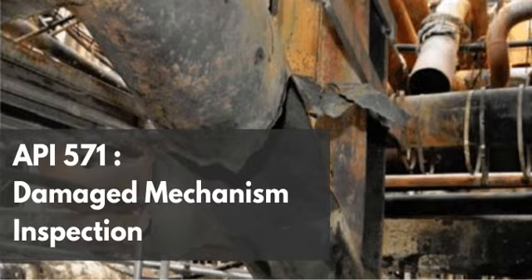If we look at how advanced steel defends itself, we look at elements like chromium. In a stainless steel, chromium is the absolute superstar. The heavy lifter. Exactly. It's the essential element that gives the metal its legendary corrosion resistance and high-temperature oxidation resistance. It acts as the shield. But carbon absolutely loves chromium. When the carbon enters the material, it forcefully pulls the chromium out of the solid solution to form those brittle chromium carbides we just talked about.